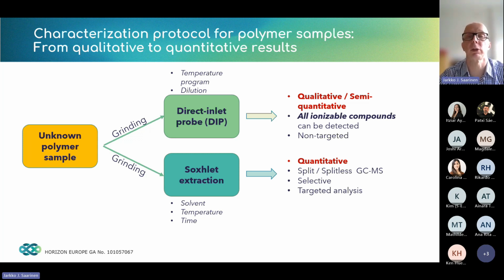As we get the mass spectra over a very wide range, we can identify the different compounds at very small amounts present in the sample. Then in the case that there are compounds that we need to quantify, we can go on for the targeted analysis, doing a Soxhlet extraction of these materials, and then go on for the quantitative GCMS analysis to get the actual accurate amount of how much of these compounds are present in the samples.